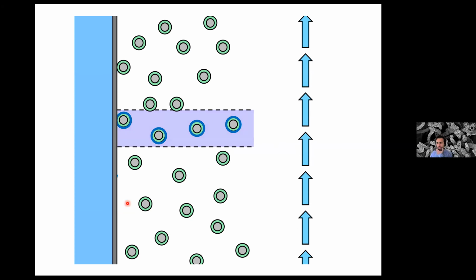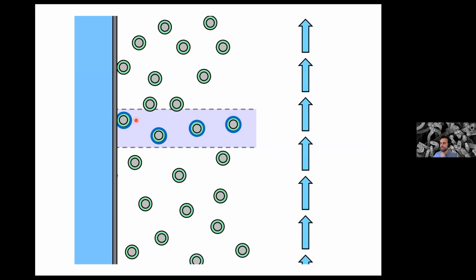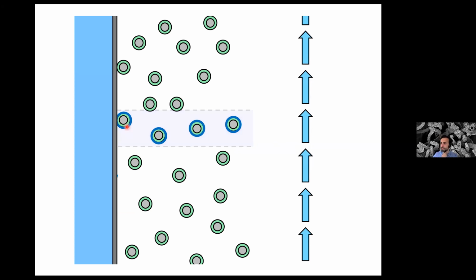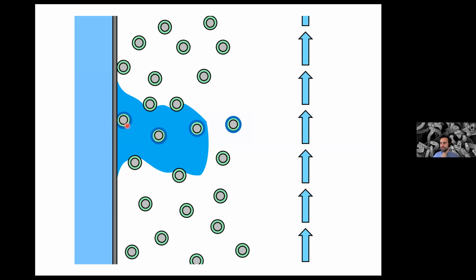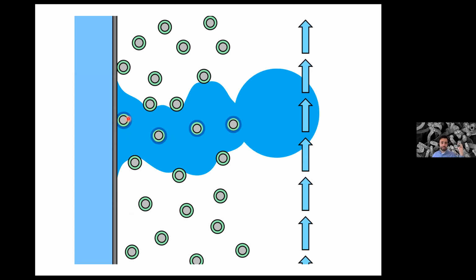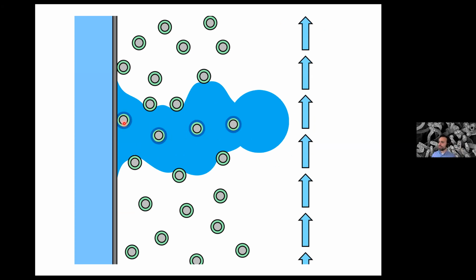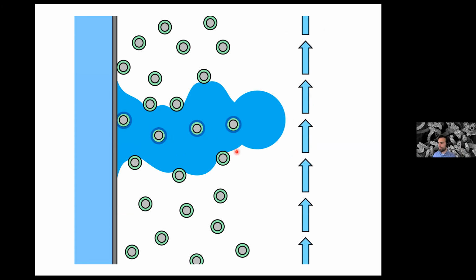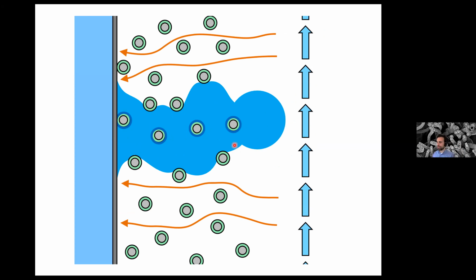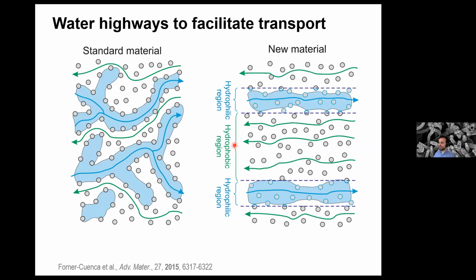And that is really what we've been thinking about for some time: can we change the local wettability of these gas diffusion layers or gas diffusion electrodes to force the liquid product, in this case water, to travel through these straightforward pathways? And as a consequence, the remaining areas will stay dry for the transport of gases, okay? So this is a fundamental problem. The fundamental challenge is really controlling multi-phase flows at a local scale. And how to do that, that's challenging because it requires modifications of contact angles and wettability through thick materials.